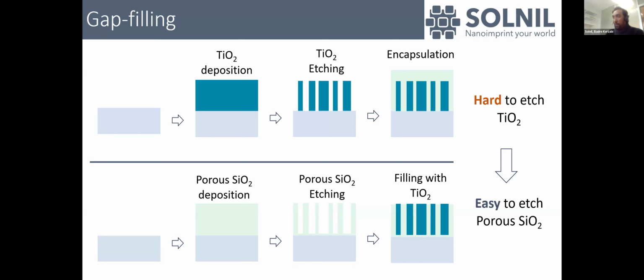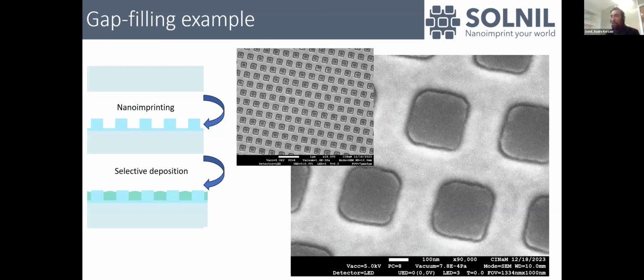It's a process that is now working well and running for small aspect ratio, with an aspect ratio of 1, and regular patterns. So now it's something that is scalable to large area. Basically, we start with nanoimprinting a low refractive index material, and by using specific deposition parameters and specific chemistry, we managed to have selective deposition only in the holes. Today it's very efficient and it works quite well for standard, uniform patterns. And now we're in the process of developing this further for metasurfaces and more complex designs.